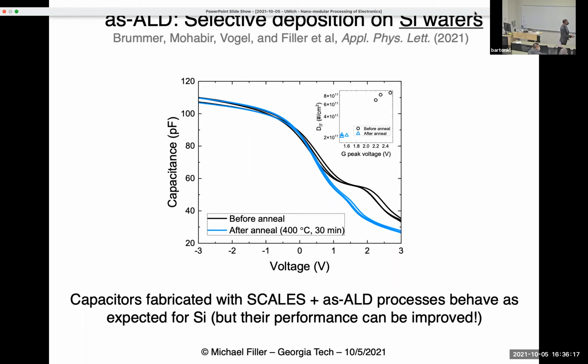And one way has been to remove this hump right here. So these are surface states. These are basically dangling bonds at the interface between the nanowire and the oxide. And it turns out with a forming gas anneal, which is a very straightforward process in the industry, you can get rid of a lot of these surface states. You can see the blue lines kind of go quickly down. And so we've dropped surface states from this level 4x or so to this level. And we think there's more room to grow.